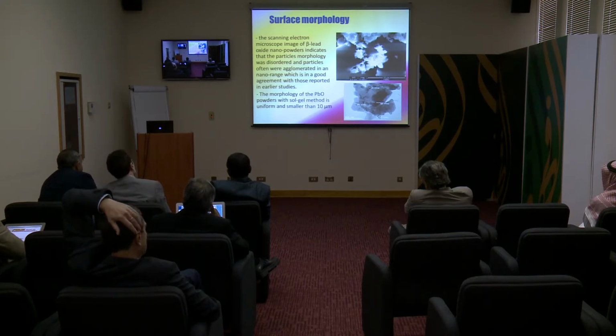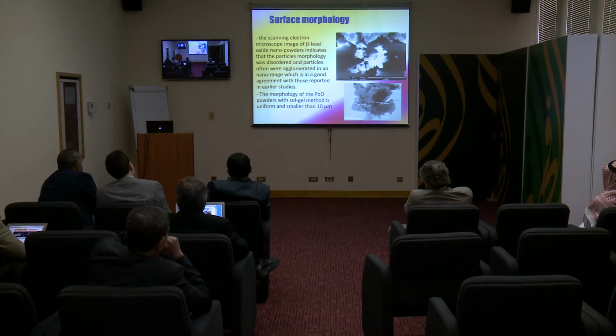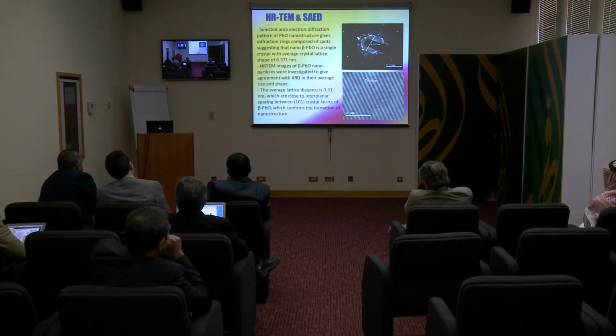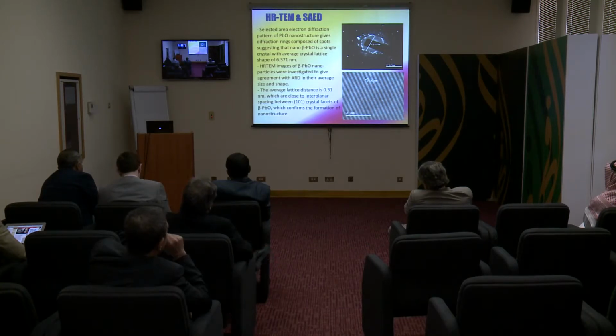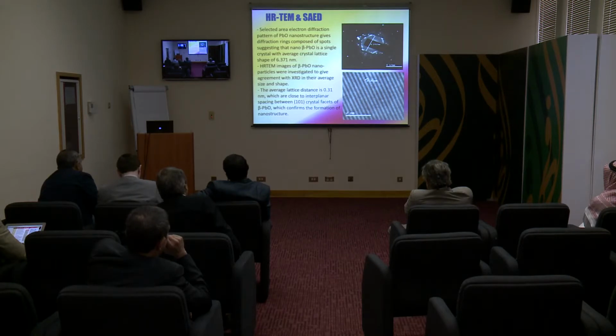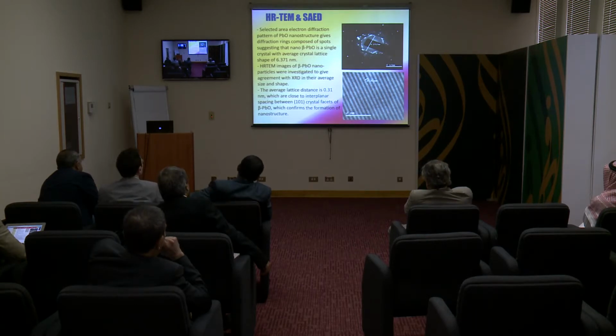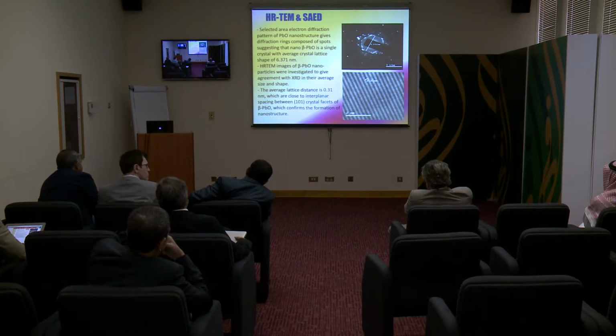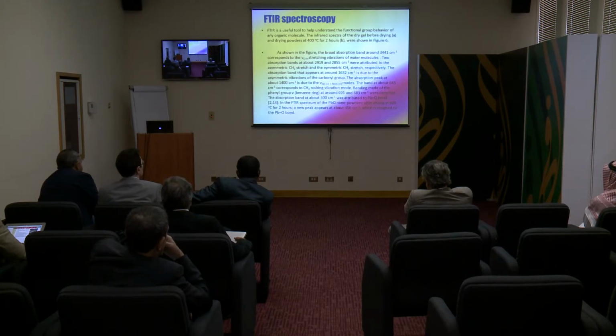And in the second image, transmission electron microscope confirmed the accumulation of the particles. High resolution and selected area electron diffraction pattern of lead oxide nanostructure gives a diffraction ring composed of spots, suggesting that nano-beta lead oxide is a single crystal with average crystal size of 6.371 nanometer. High resolution transmission electron microscope image of beta lead oxide nanoparticles was investigated to give agreement with X-ray diffraction in this work in the average size and shape. The average lattice distance is about 0.31 nanometer, which is close to the interplanar spacing between (101) crystal face of beta lead oxide, which confirms the formation of nanostructure.